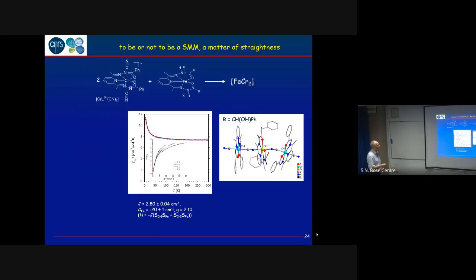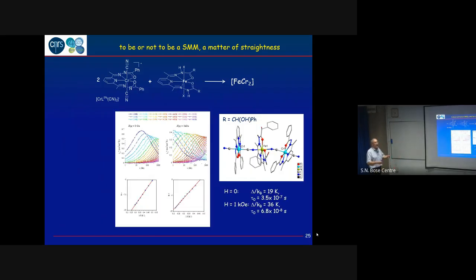The plot here shows chi T versus temperature. I don't know if you are familiar with chi T. It's just a different unit for mu effective. But what you see is, as you decrease the temperature, chi T increases, and this is a sign of ferromagnetic behavior. So indeed, we switch on ferromagnetic exchange between these centers, and for this compound, we can confirm that we still have a large negative magnetic anisotropy. And you understood now the story. When you have that, you can expect slow relaxation of the magnetization, and this compound is a single molecule magnet.